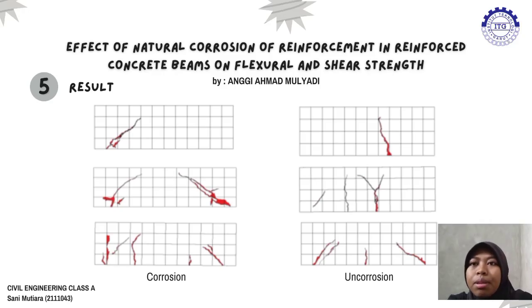From the crack pattern, in uncorroded reinforced concrete beams, cracks occur in the center area as flexural cracks or moment cracks, and the crack pattern in the corroded reinforced concrete beams has many shear cracks. Because the shear failure of corroded reinforced concrete beams is largely affected by the load borne by the corroded stirrup.